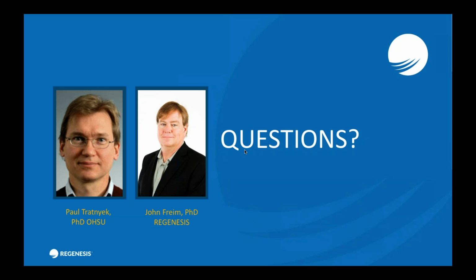This question is for John, and it's regarding Aqua ZVI. What is the viscosity of Aqua ZVI when it is injected into the ground? Okay, that's a great question, Dane. So the way this works is that when the material is shipped, it comes as a fairly viscous suspension, like I said earlier, 2,000 to 3,000 centipoise. But when it's diluted in water at field applications, it's typically about 1 to 2% of the material in your mix tank. And when it's mixed and suspended, the viscosity is essentially the same as water.